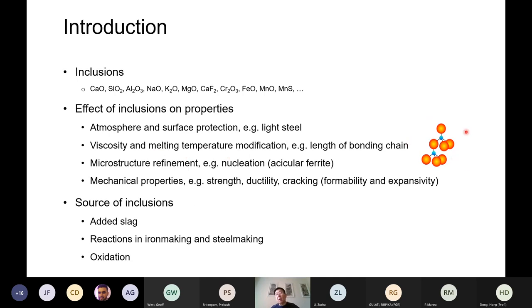Here is a molecular structure of silicon oxide. You see each silicon is linked to four oxygens, and each oxygen is linked to two silicons, so it is silicon dioxide. This chain can go very long and make the viscosity very high. To reduce that, we introduce calcium oxide, which will break those long chains into short ones, and the viscosity will be improved.